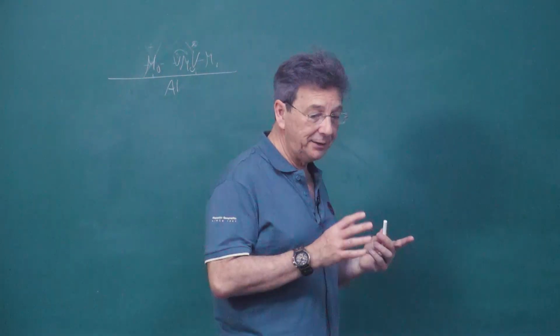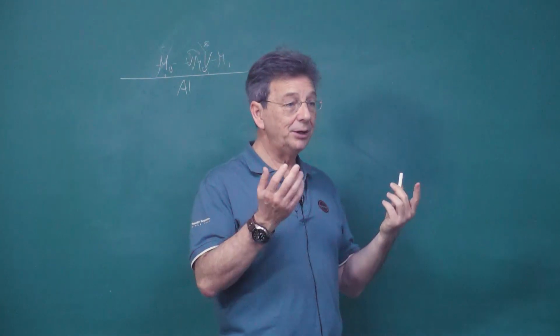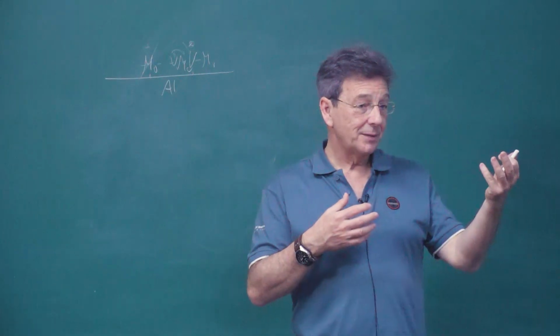There is one scenario when you are using additives and promoters that you will see. There are some additives that don't like to interact with each other. Like for instance, vanadium and molybdenum, they are acidic. So acidic and acidic, they don't really attract each other that much. However, if you put something which is more acidic and something that is more basic, then they will like each other.